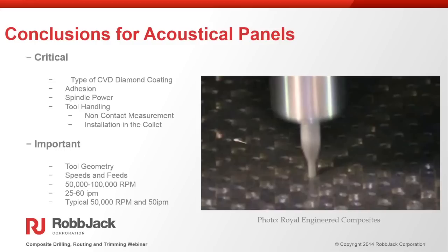The other problem that we ran into was, when we first started this testing, we weren't getting the high number of holes and predictability. It was very varied. And when we looked into it a little bit further, and the customer looked into it, we found that the speeder that was used on the spindle was actually lowering the RPM. So it's really important when you're doing applications to make sure that we talked about rigidity in the fixturing, but also the spindles, the speeders that you're going to be using. For this example, the speeder was slowing down, so the feed rates and chip load per tooth was not consistent, and then that was throwing in the variability. So once we switched to a really nice, high-quality speeder, it solved all those problems.